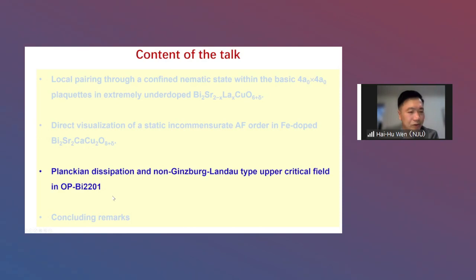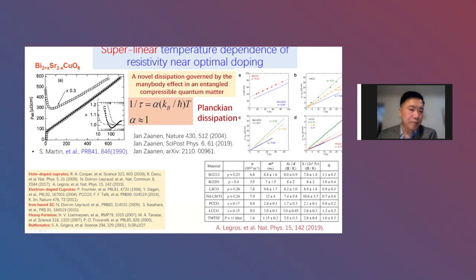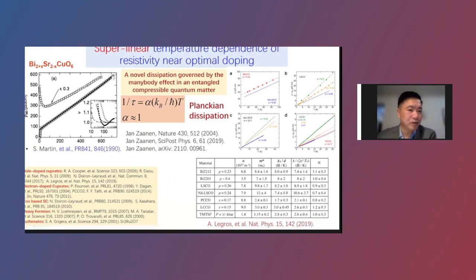Then I come to the third piece of work, in which I will show you the normal state of BSCCO 2201, which has Planckian dissipation. And we found that the upper critical field is a non-Ginzburg-Landau type, okay? We all know that in cuprates, there was very strange behavior for the so-called BSCCO 2201 without the lanthanum doped one. In early times, in 1990, this is a canonical curve, okay? So the resistivity goes from Tc about 7 Kelvin to 700 Kelvin. So that violates the so-called phonon scattering.